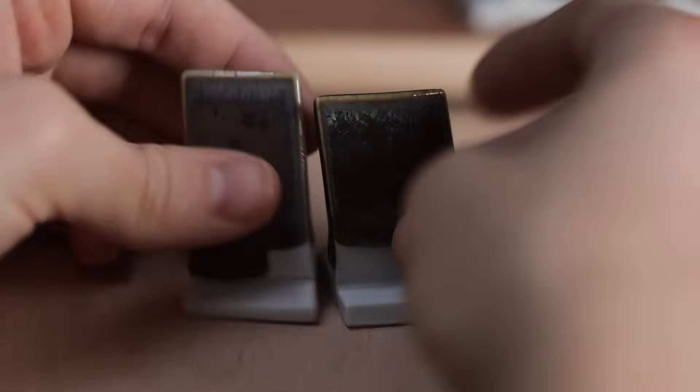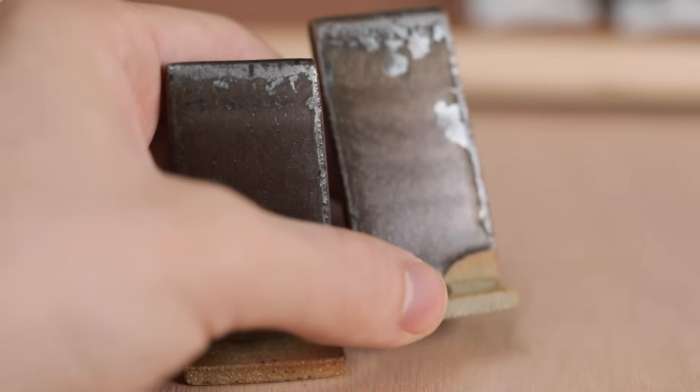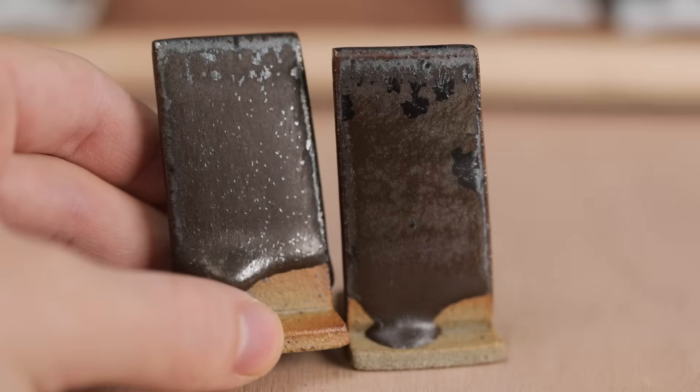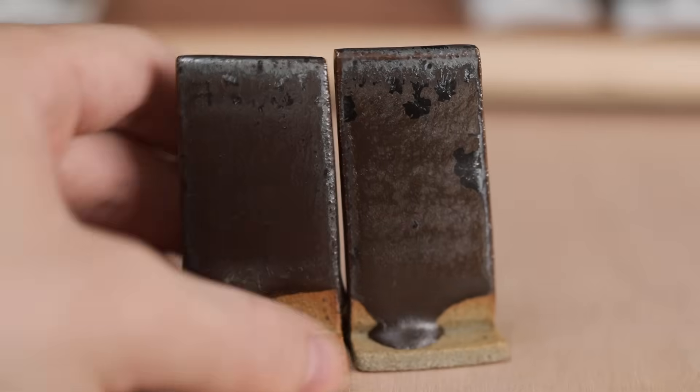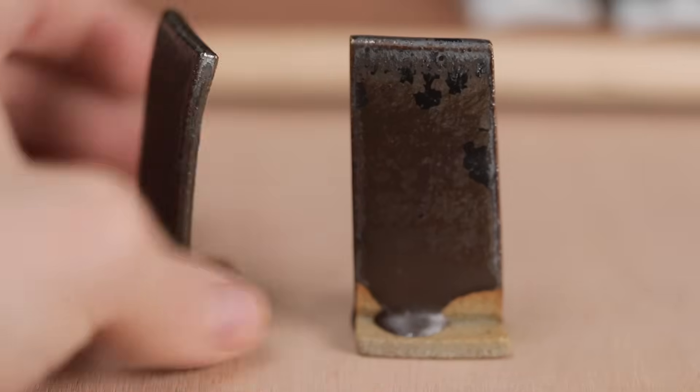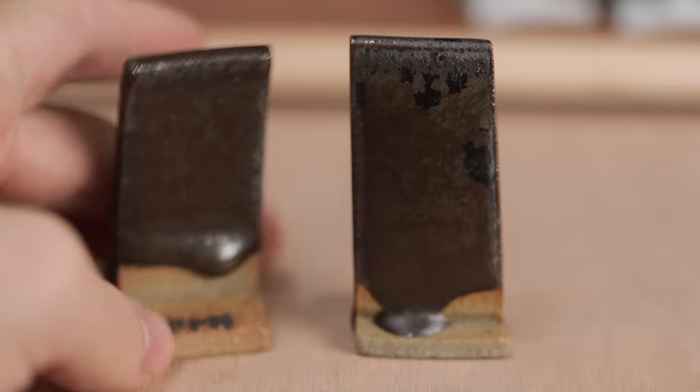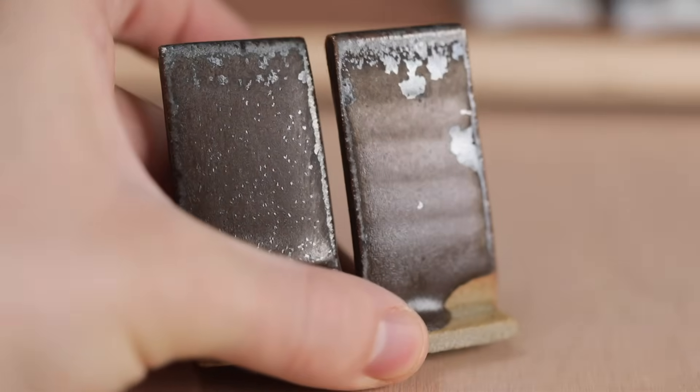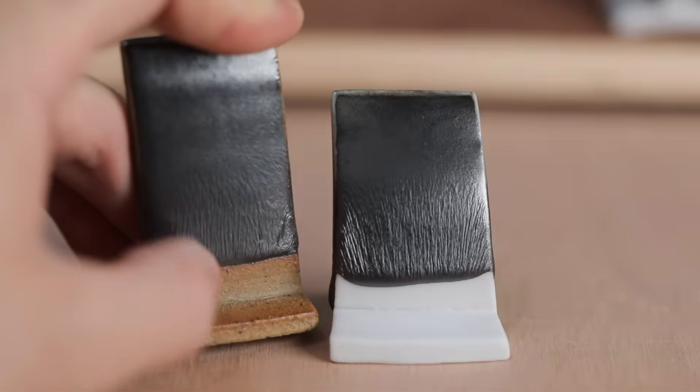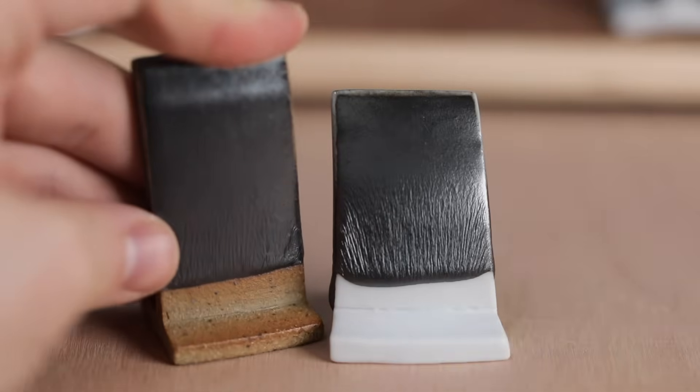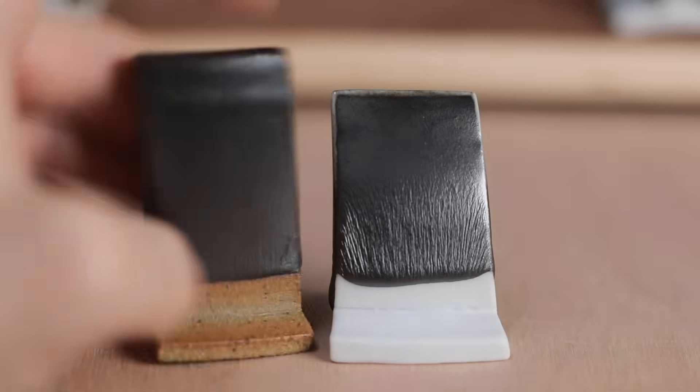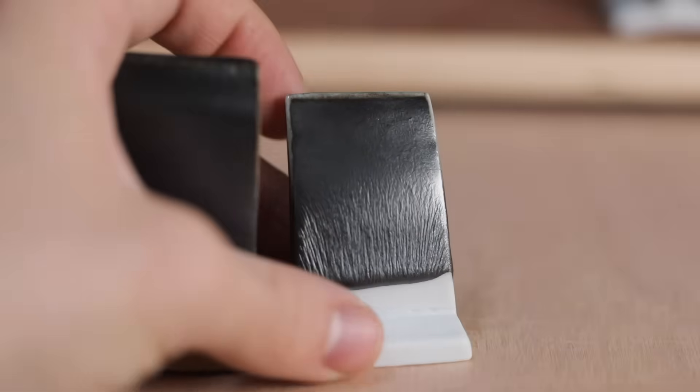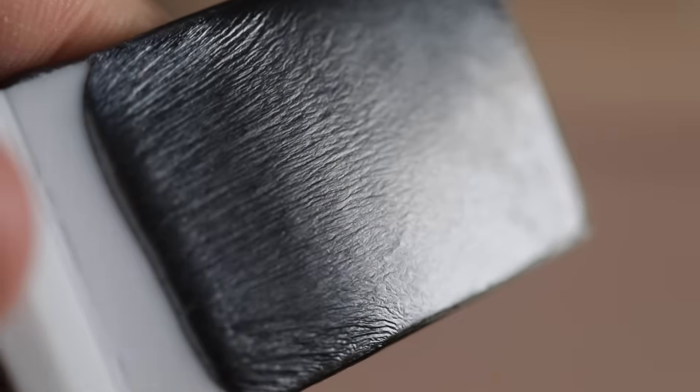This next one is the exact same recipe, but I increased the clay content by 20%, which made the brown stronger, but also caused the crystals to grow in smaller little specks. So I can't imagine these getting much use, but they are very pretty tiles. Like these ones too, which again I can't really use because of the Manganese content, but it feels incredible and is so shimmery and metallic. And as it flows, it creates these interesting streaks.